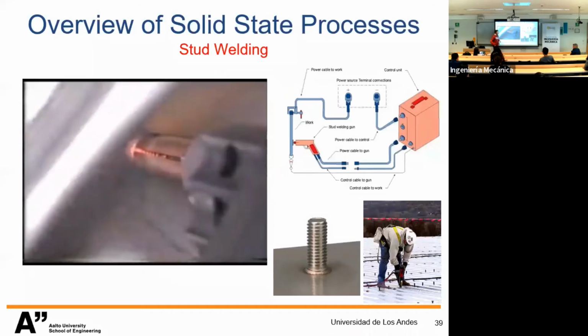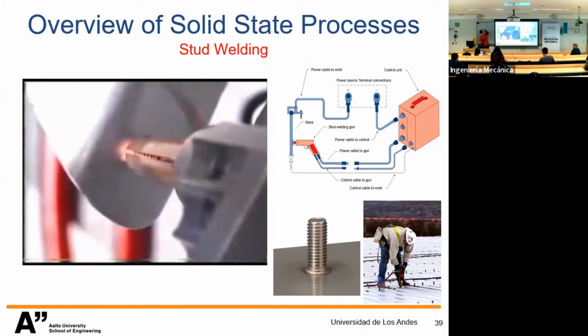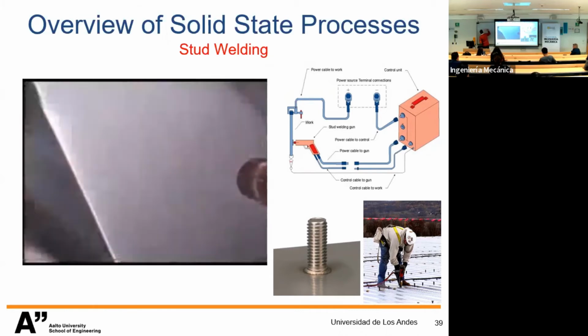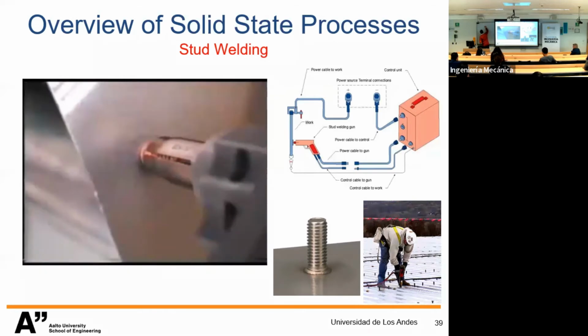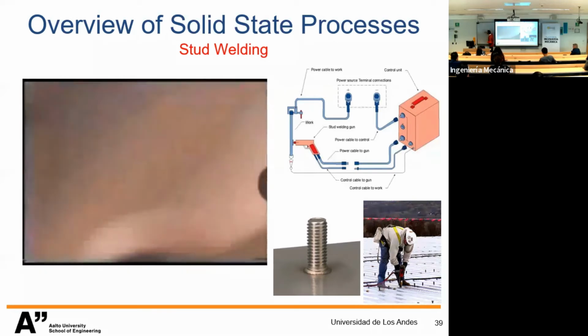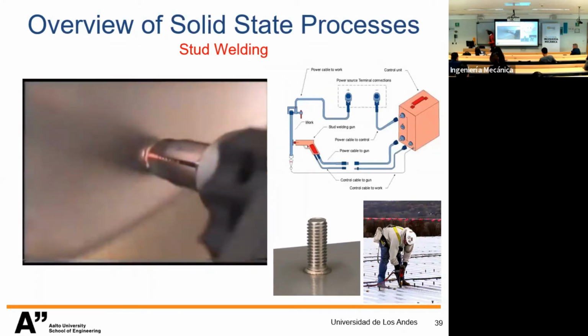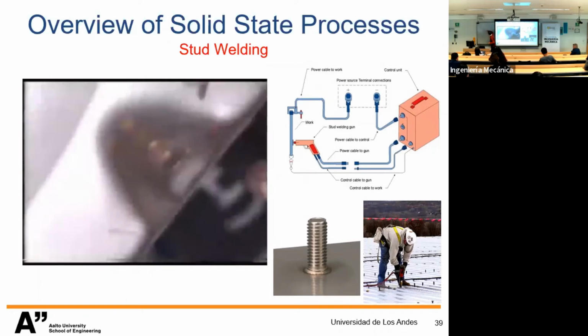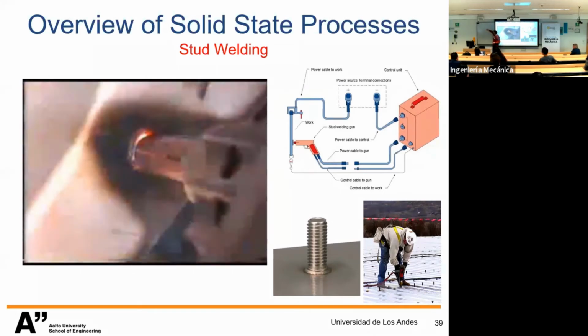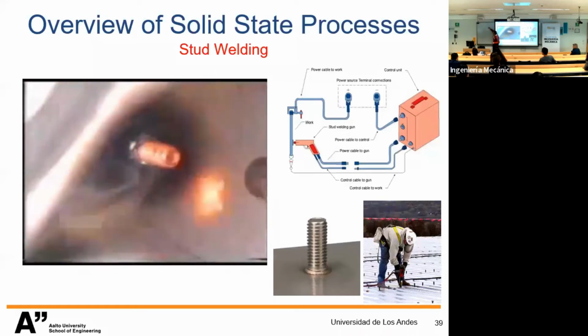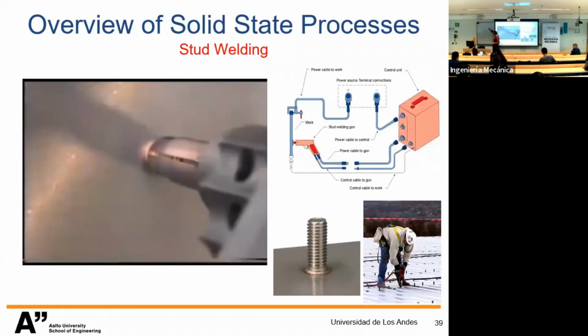It's the same as the flash weld. You have a very specific profile where you have something like this in the stud, the body of the stud, and this creates the distance in between the base material, and then you have the sparks with low voltage, okay, and high current.